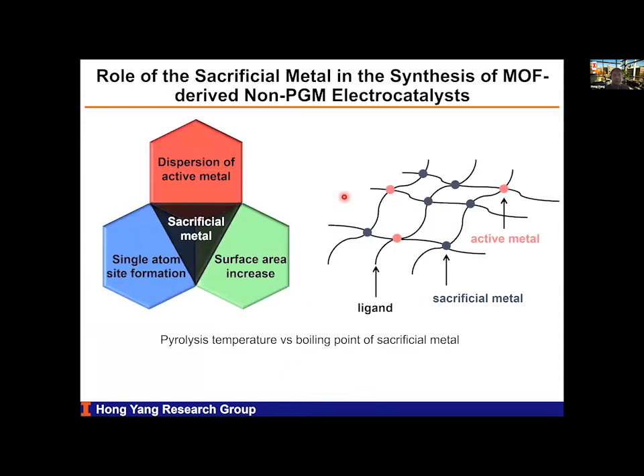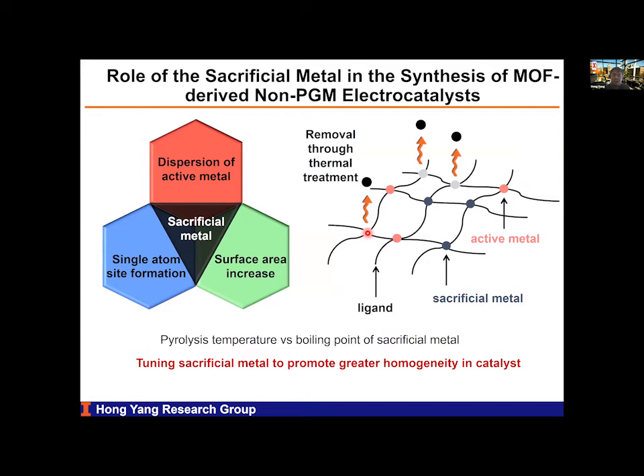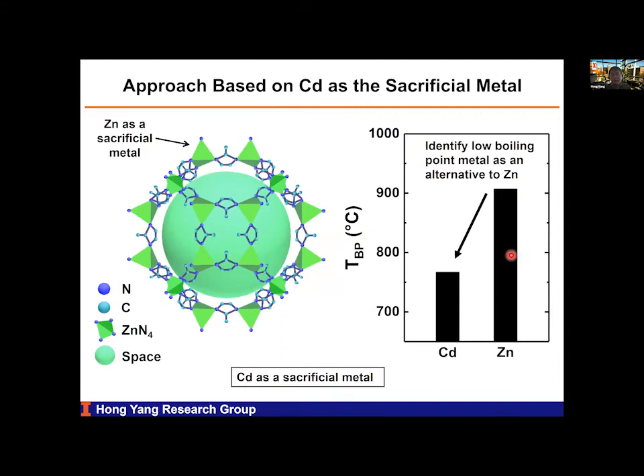So the background is that for typical MOF-derived non-PGM catalysts, for the metal center, it could be iron, cobalt, or manganese. What happens here is that through the pyrolysis, some of these active metals are maintained, but the sacrificial metal, for example, these dark spots represented in this chart, should be removed during the process. And typically, this dark metal is zinc. So to test the concept, we identified one of the metals, cadmium, which has a lower boiling temperature, and we can see whether that can still maintain the carbon-nitrogen structure, but reduce the formation of nanoparticles by lowering the temperature.